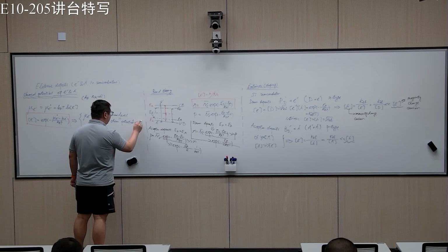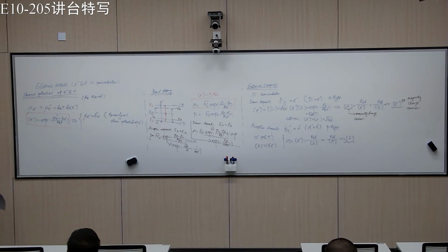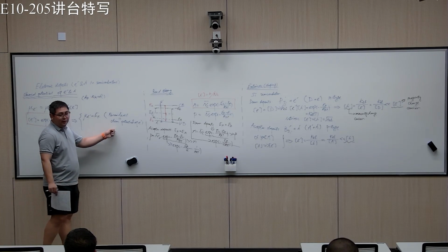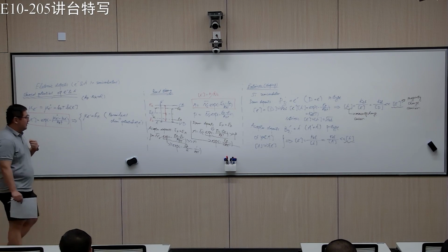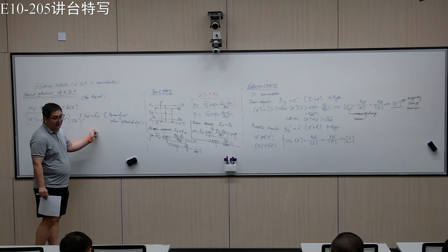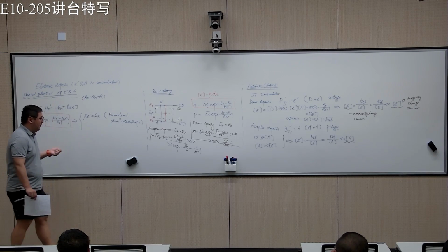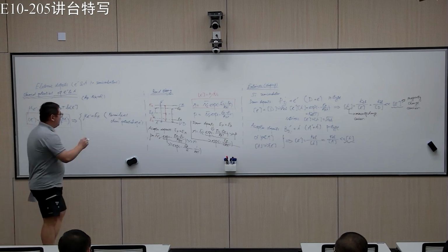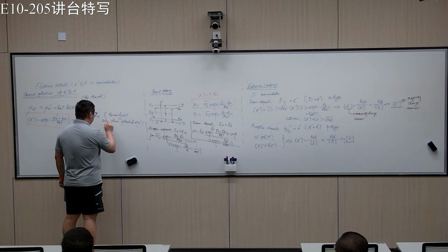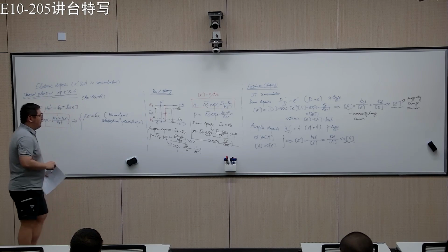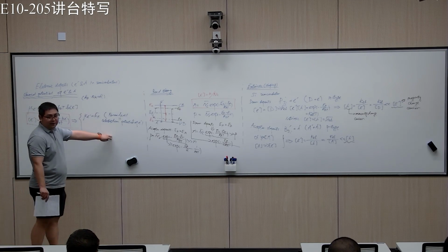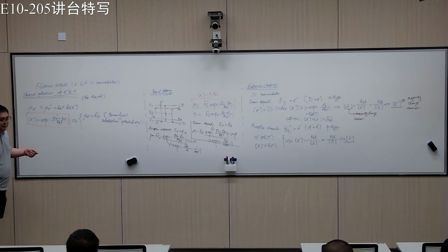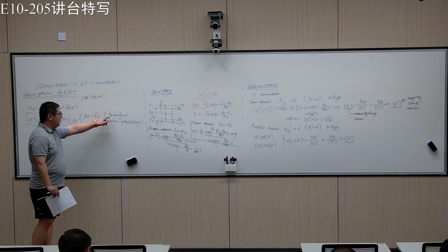Potential of electrons. Okay, so in a lot of the solid state physics textbooks, you will find this conclusion. Of course, it's not 100% correct. So what I want to say is that later we're going back to this. It's actually the electrochemical potential of electrons, because sometimes you can have an electric field and electrostatic potential. But let's not go in there just yet. So here, it's sufficient to know that the chemical potential of electrons is basically the Fermi level.